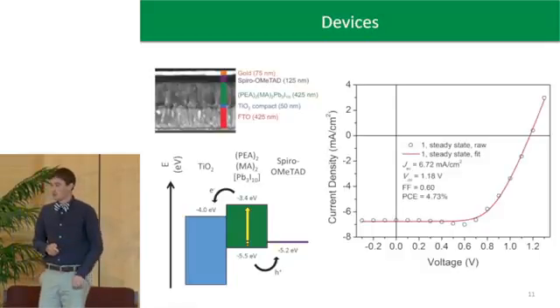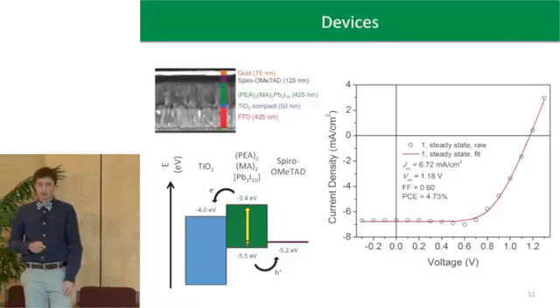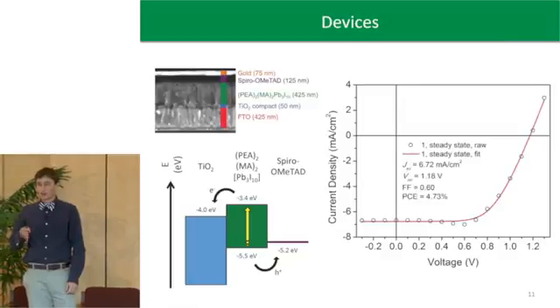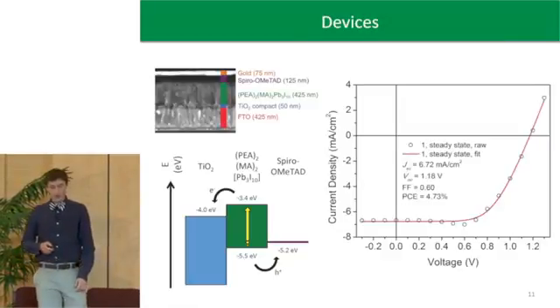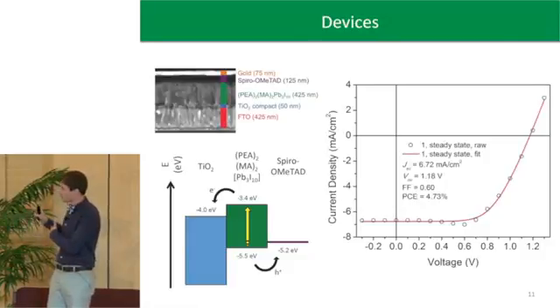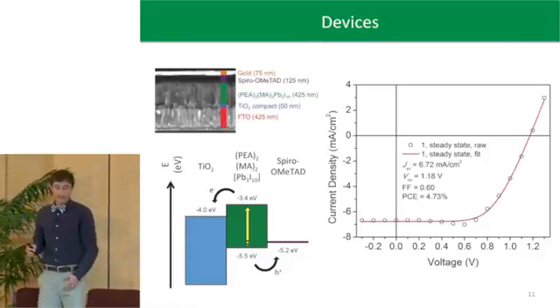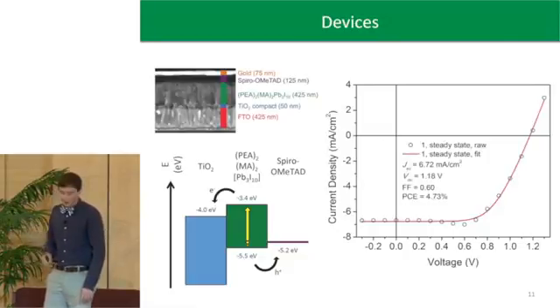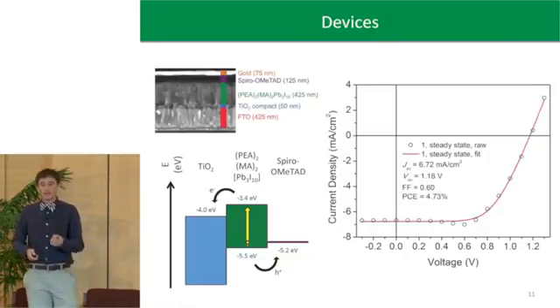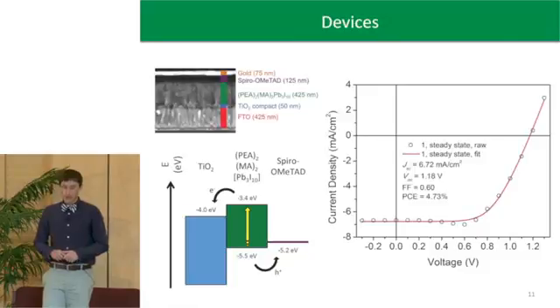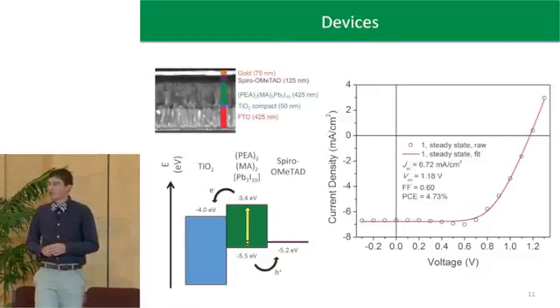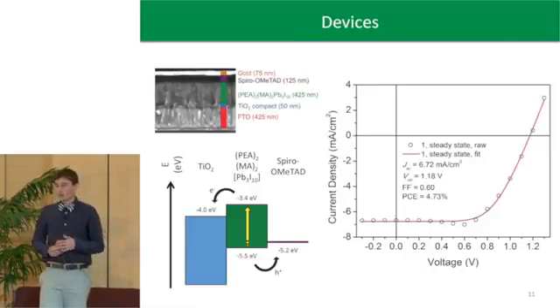To test these devices, we took IV curves. Essentially, you are sweeping the voltage and measuring the current response when you're illuminating the device. What you want to see, as I've plotted it here, is high voltages, out to the right, and high currents, in this case negative currents, down to the bottom. Importantly, this material has a high VOC, which is where it crosses the x-axis. It's around 1.18 volts. This is a full 100 millivolts higher than a record cell for methyl ammonium lead iodide, and in fact most of those cells will be closer to around 1 volt. So this is a higher VOC.